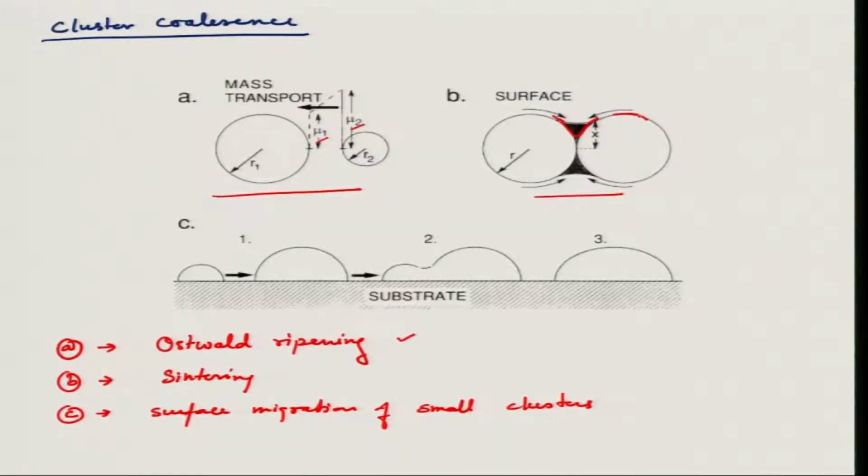It is shown that the energy of atoms on a convex surface is higher than on a concave surface. So, atoms will tend to move towards this neck region from both, and slowly they will fuse and form one stable nucleus, which is larger in size. This is how different nuclei merge together.